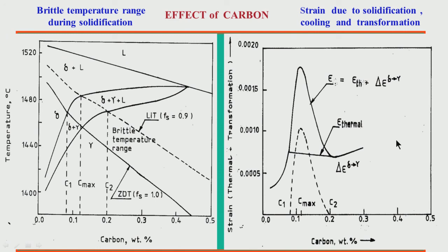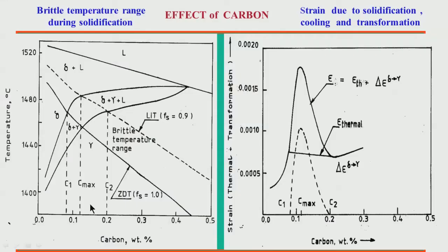This is called the so called depression grades, the so called peritectic grades. Basically it means the starting of the peritectic chemistry. Peritectic starts from 0.1 and goes up to 0.5, but as we have shown here, the chemistry range around 0.07 to around 0.17 or 0.18 is the real matter of concern.